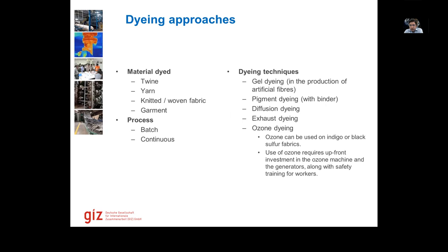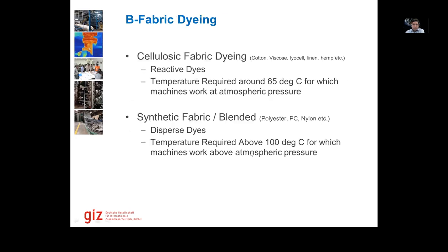And if we are using ozone machines, there's upfront investment required in the ozone generator, and also safety training of workers is needed, because with ozone we also get some health and safety hazards as well. There is also cellulose fabric dyeing, where we need reactive dyes. The temperatures are around 65 degrees Celsius, and machines work at atmospheric pressures. For synthetic or blended fabric, disperse dyes are normally used. The temperatures are above 100 degrees Celsius, and the machines also need to be pressurized in this case.